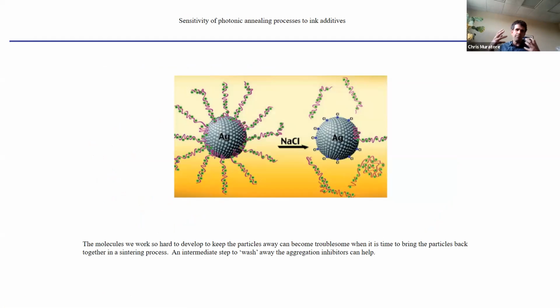If you have very small particles, there's a driving force for them to aggregate together. And you can inhibit that aggregation by attaching these polymers on the surface. Now the trouble is, let's think about what we want to do. We want to have a stable suspension of these particles so that we can apply them to a surface, and the process isn't going to change over time. But once they're on the surface, we want them to interact with each other.